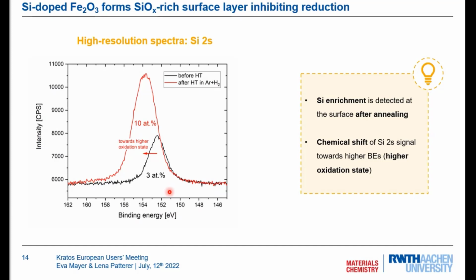So it seems that silicon is moving towards the surface as we have this heat treatment in the hydrogen plus argon atmosphere. And we can also see a chemical shift towards higher binding energies, which means we have a higher oxidation state of silicon. So our interpretation would be that when we have the silicon doped iron oxide thin film that we form during the reduction process, the silicon oxide rich surface layer is inhibiting the reduction process.